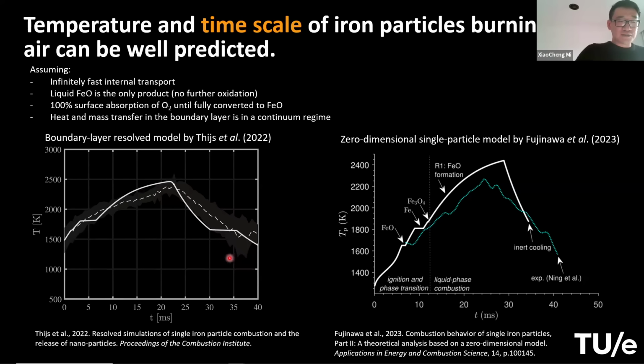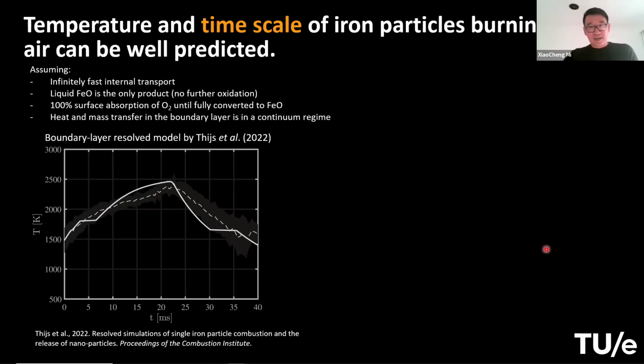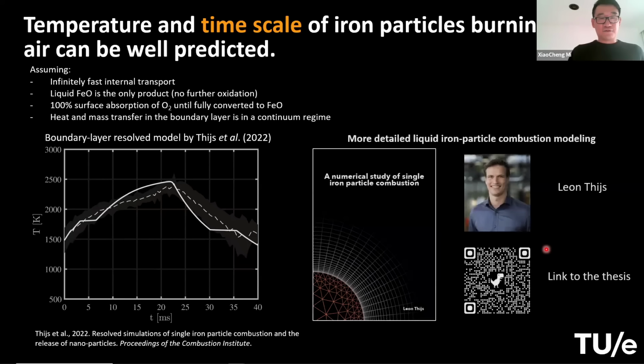You see the overall trend matches pretty well. That means we are able to predict the temperature of the particle and also the time scale of the combustion process. And then later, with Aki Fujinawa, we developed this zero-dimensional, even simpler iron particle combustion model, which also matches the results very well, both in time scale and temperature. And of course, at higher oxygen concentrations, the results are not yet perfect. For more details, you can look into Leon Thijs' PhD thesis. He looks into what the effects are and how to go beyond these assumptions. So here I won't elaborate on this point.